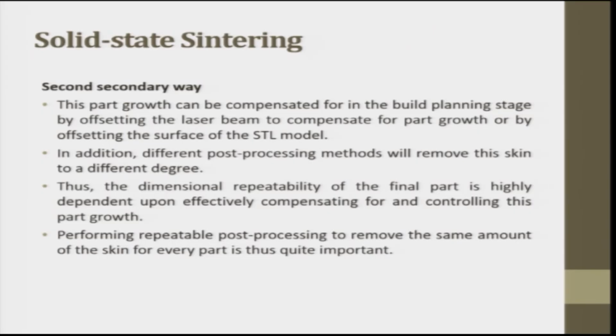This part growth can be compensated for in the build planning stage by offsetting the laser beam to compensate for part growth, or by offsetting the surface of the STL model. So, this is also a very important point. In addition, different post processing methods will remove the skin. Thus, the dimensional repeatability of the final part is highly dependent upon effectively compensating for and controlling the part growth.